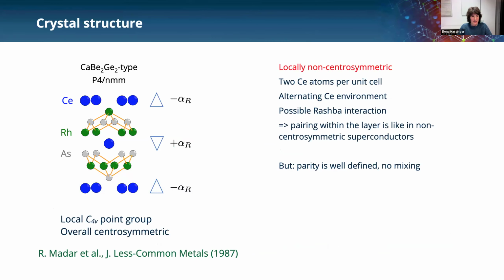Here's the crystal structure of this material, and it's not the normal 1-2-2 structure, it's the calcium beryllium 2 germanium 2 type structure. In this structure you have two cerium atoms per unit cell, and they have an alternating environment. You can see that this cerium has a rhodium layer above and an arsenic layer below, and the next cerium has an arsenic layer above and the rhodium layer below. And so you lack mirror symmetry, and that's how you can get Rashba spin orbit coupling at the cerium position, which alternates the sign when you go from one cerium layer to the next.